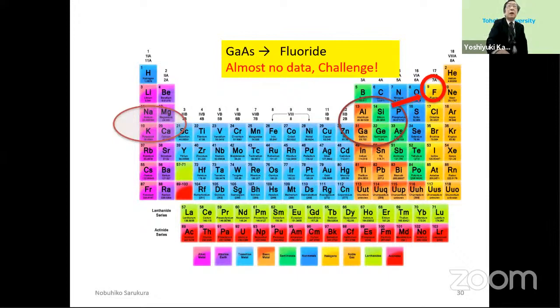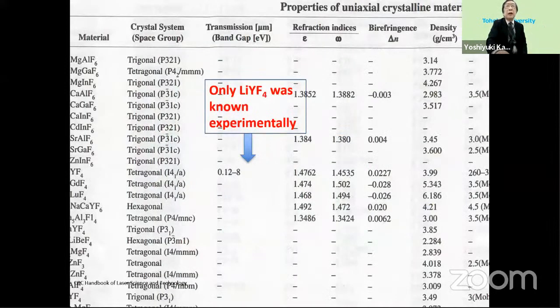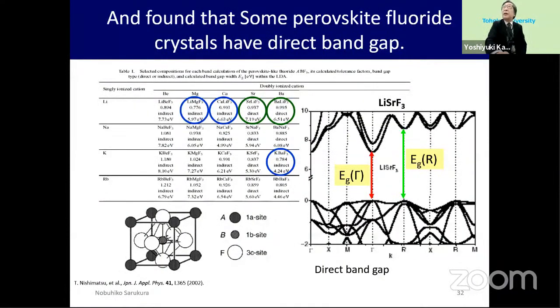It's a challenge because 10 years ago there was almost no experiment. Only one experiment existed, the lithium yttrium fluoride, only one. And we have surveyed many types of fluoride. On the right, you can see magnesium aluminum fluoride, magnesium gallium fluoride, and computed many things. And Dr. Nishimatsu worked on this one. It's very time consuming and tedious work, but he has found several good ones.